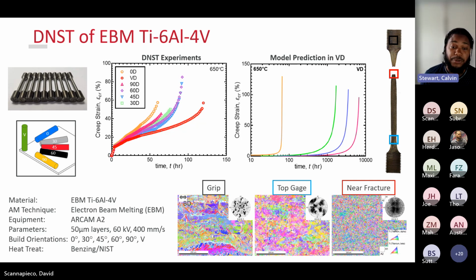But also using well-posed models, again, we're able to predict the conventional response of any of these different build orientations. Here we see our model predictions for the vertical direction, which we found was the best performing direction. And we're predicting out to, looks about like 8,000 hours of life. And look, our experiment was less than 125 hours. So this is a very incredible tool in your wheelhouse. It allows you to screen a material based on processing parameters, and it allows you to predict its full-scale performance in a really narrow period of time. Next slide.